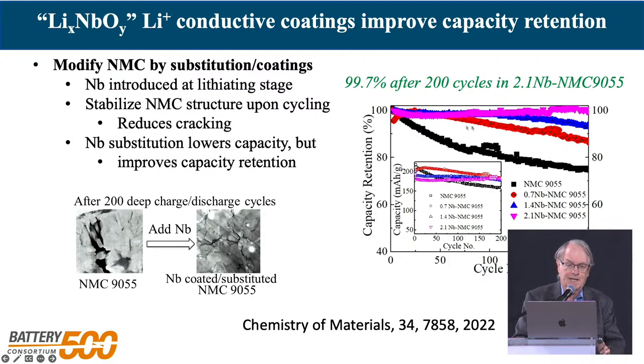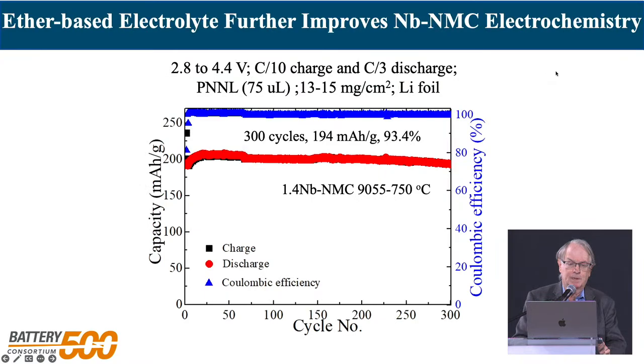But this is using standard electrolytes. We want to go to our new electrolyte, our special electrolyte, which is an ether-based electrolyte using LiFSI as the salt. And you can see the coulombic efficiency is 100%, and the capacity here fades very little over these 300 cycles. And it turns out with this electrolyte, we're getting better capacity than with the earlier one. So we're making progress. We believe we can get 1,000 cycles out of these systems. It's not clear niobium is the optimal material, but we've got a clue that we're on the right track.